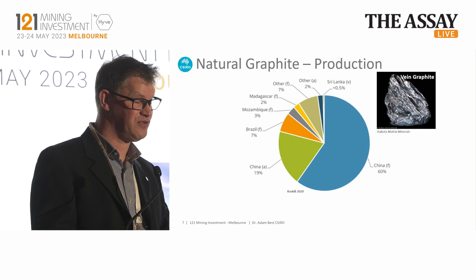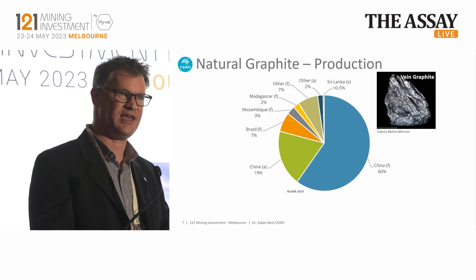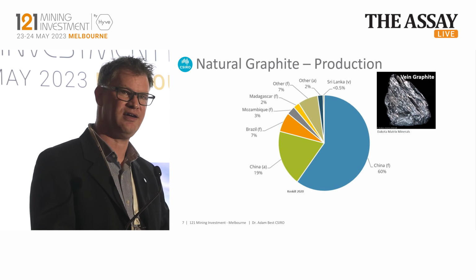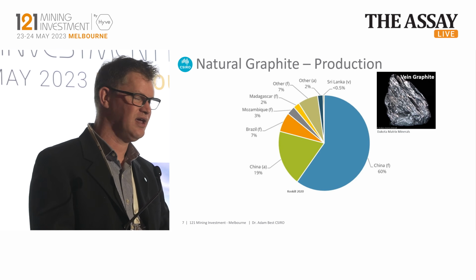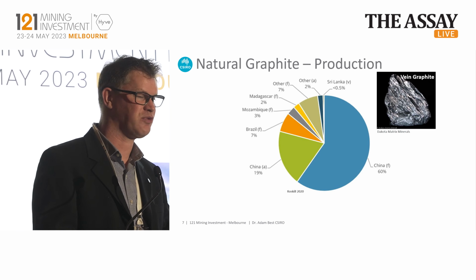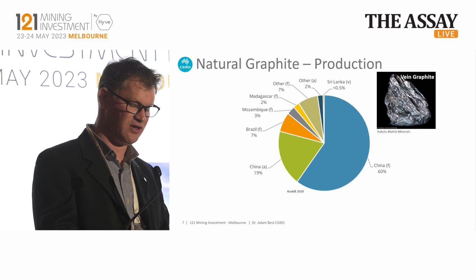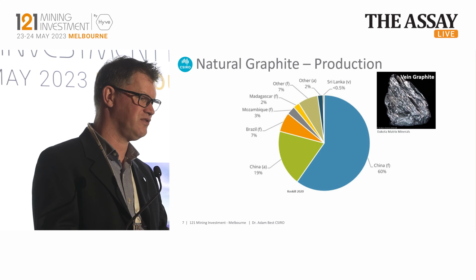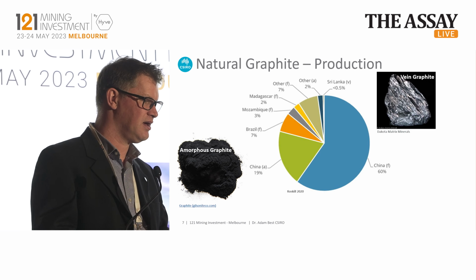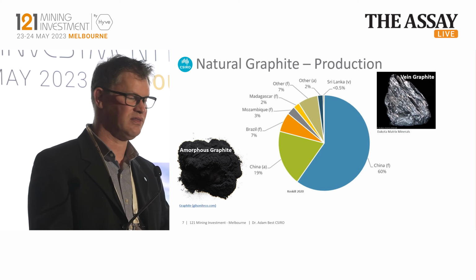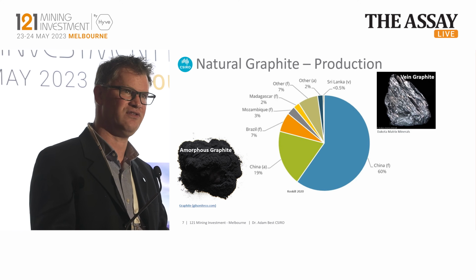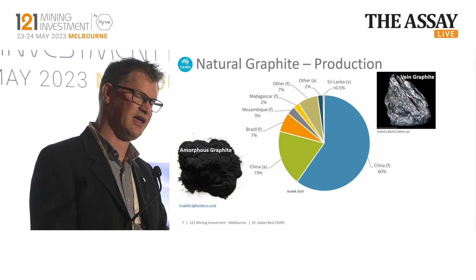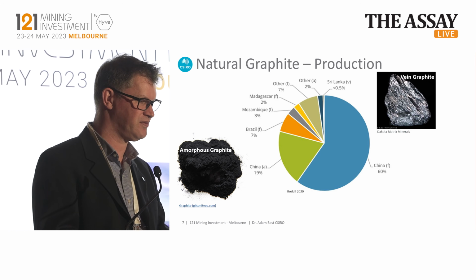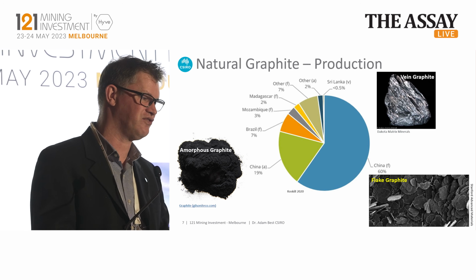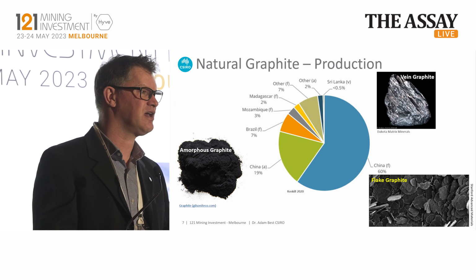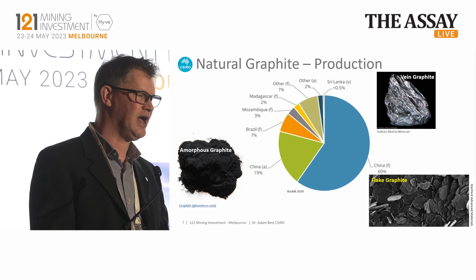There's also different types of graphite. So vein graphite is a particularly interesting graphite that's potentially found in Sri Lanka. It's probably the most purest form of graphite. It's the easiest to use. It doesn't require as much processing to access, so it's a particularly useful type of material to get, and Sri Lanka produces quite substantial amounts of this material. Amorphous graphite is obviously the more common form of graphite that we find, and is used as a conductive additive inside batteries, and that can be made by a number of different methods. And the one that we're particularly interested in is flake graphite, and this comes from a range of different natural graphite sources.